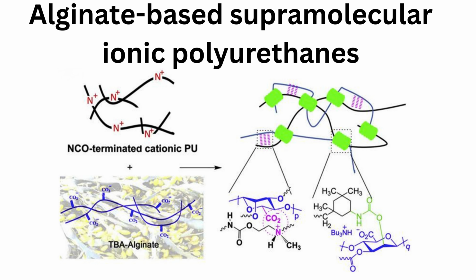These interactions confer simultaneous high rigidity and toughness to the elastomer, demonstrating broadly tailorable mechanical properties modulated by alginate content, reaching a tensile strength of 48 megapascals and Young's modulus of 93 megapascals. The elastomer displays rapid and exceptional self-healing capability, with healing efficiencies of 87.3% in the first cycle and 70.2% by the third healing cycle. Pi-pi stacking.